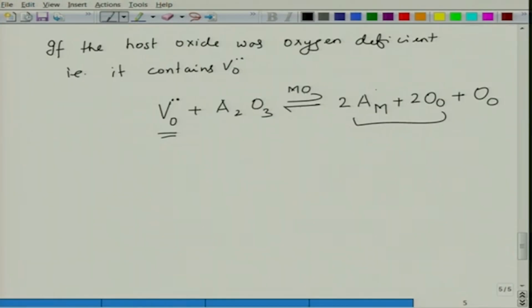So, you can write this as 2. So, this can be, this is positively charged, this is again positively charged. So, you have positive charges balancing each other, the sites balancing each other, and so essentially you can write this as 2Am• plus 3Oo. Site balance is there because you have two metal sites, and one of the oxygen sites is compensated by this site, and for the two metal sites you have two metal sites. Okay. So, site balance, mass balance, and charge balance is there. All right. So, this is how you can use it to your advantage.